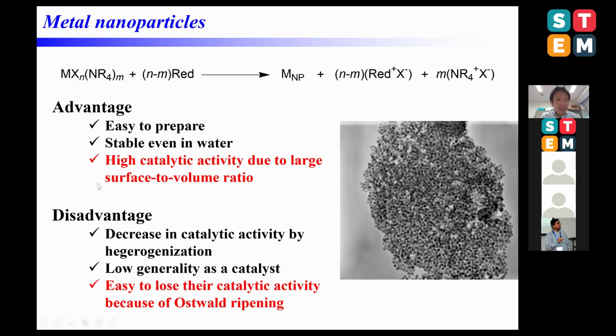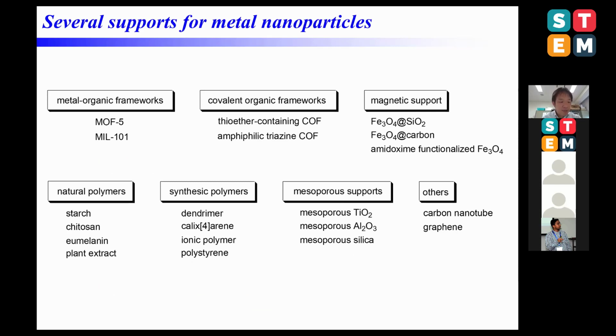However, they have some drawbacks. One major drawback is that the metal nanoparticles tend to lose their catalytic activity during use. This is a consequence of the formation of aggregates owing to their high surface energy, via so-called Ostwald ripening. For this reason, a number of different solid support materials for metal nanoparticles have been investigated, including metal organic frameworks, covalent organic frameworks, magnetic supports, natural polymers, synthetic polymers, and mesoporous supports, and so on.